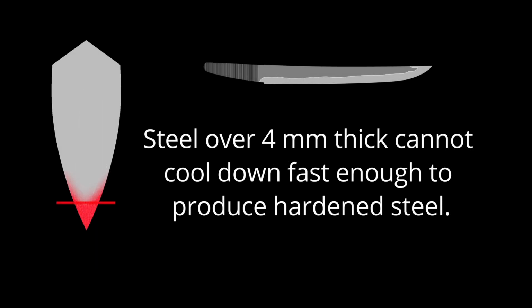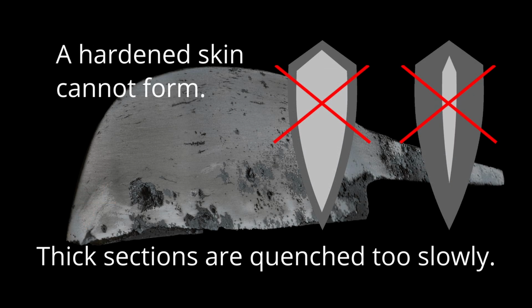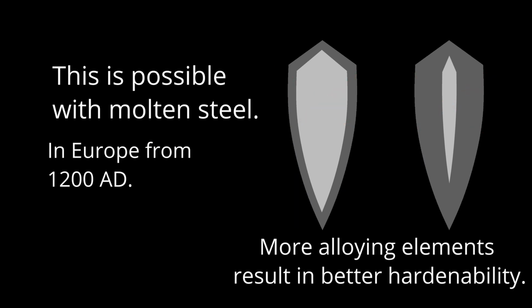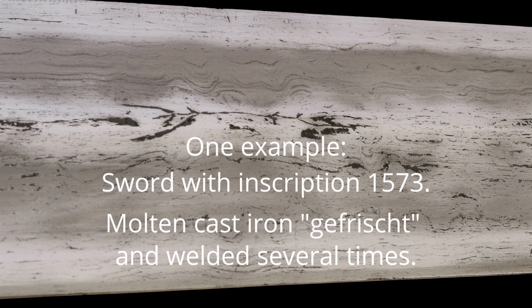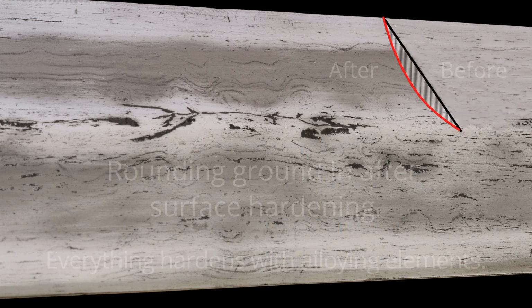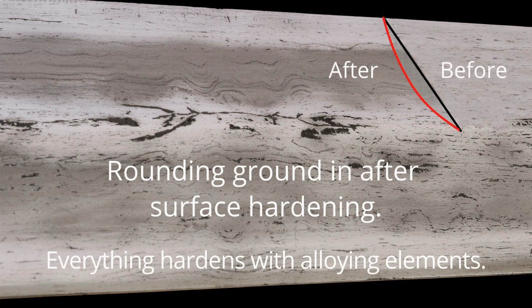The higher the steel quality, the purer the steel and the more optimal the carbon content. The broader the hardening, the more resilient the hardened steel and the higher the hardness that can be achieved. I have tempered many such blades. If everything is optimized, such a steel made directly from iron ore can only be hardened to a thickness of 4 mm. Then the formation of martensite quickly stops and the rest of the blade no longer accepts hardening.